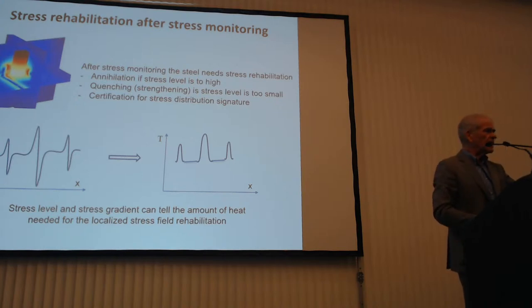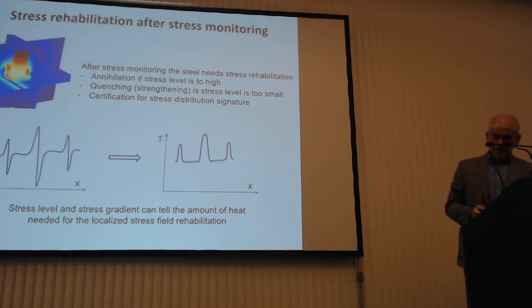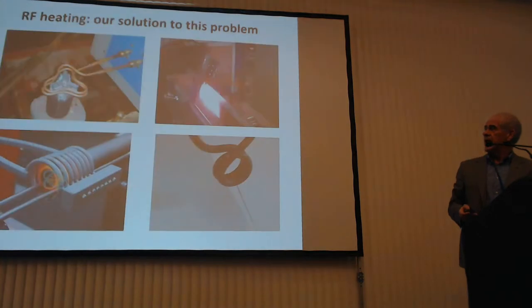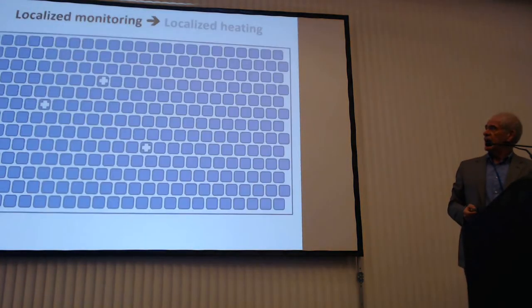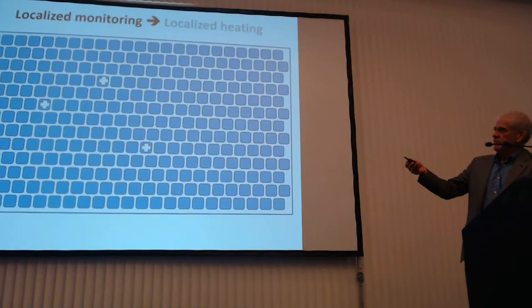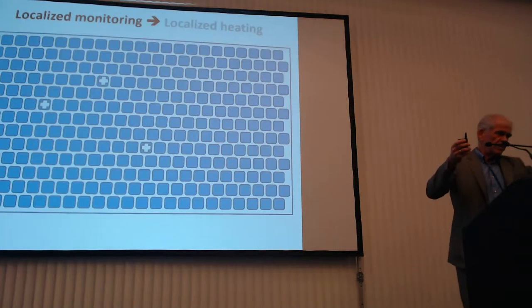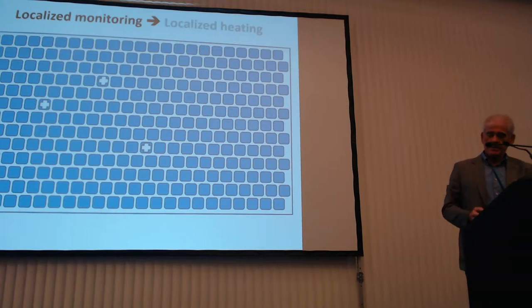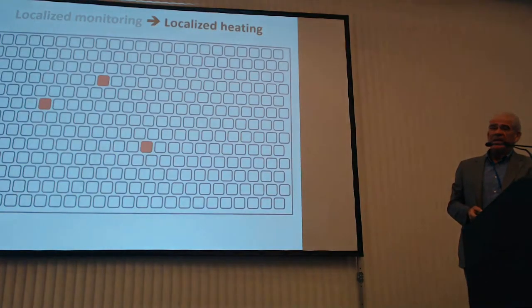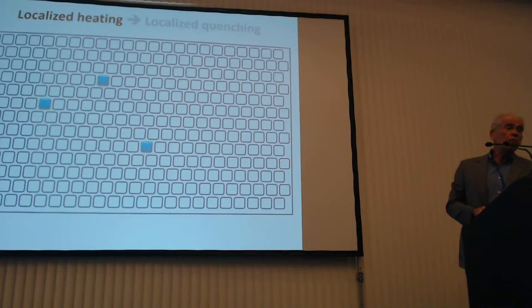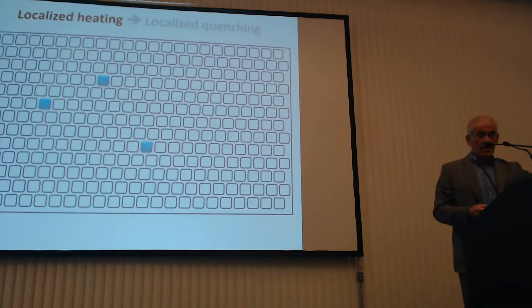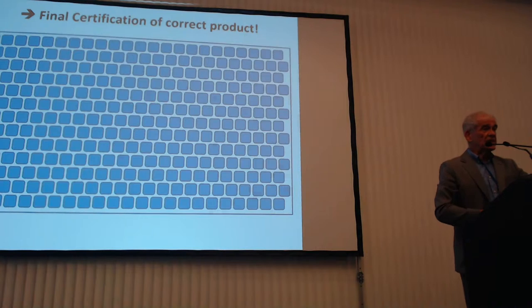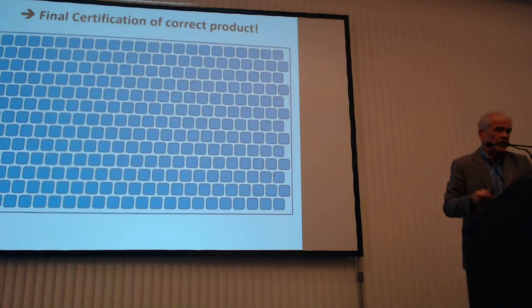So we developed special types of inductive probes in order to obtain residual stress annihilation. And these inductive methods are in principle used as depicted in these three following slides. First, we detect where the residual stress existence, imperfection, is. Then we apply inductive heating in these positions, and if needed, we apply also quenching techniques. I mean, not only to annihilate the stresses, but also to replace them at the proper level. And then we monitor again the stresses and we find them in a good condition.